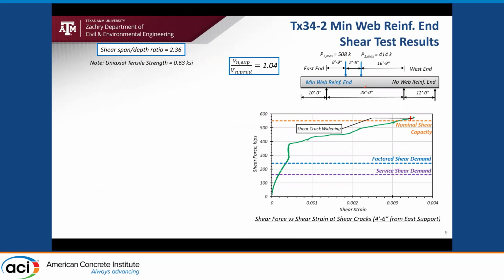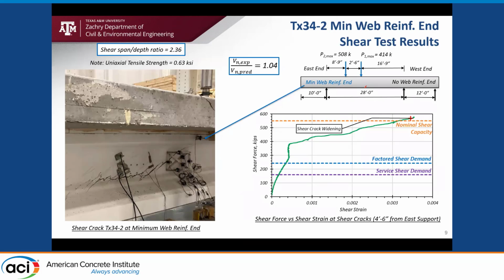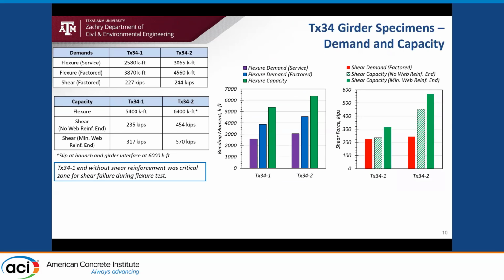Then we wanted to test the minimum web reinforced end of that specimen. So we again tested the shorter span, and we got similar web shear cracking for this specimen as well. And we had a pretty high shear capacity for this specimen of about 550 kips, which was pretty close to the predicted values.